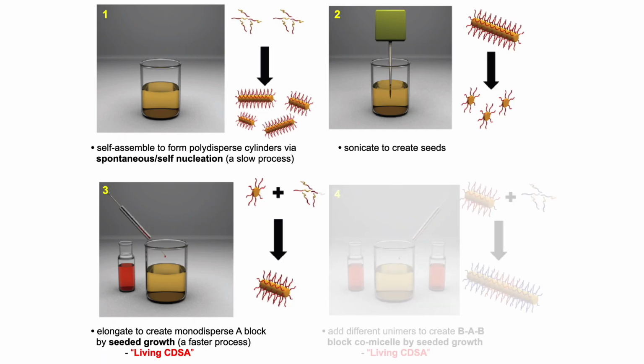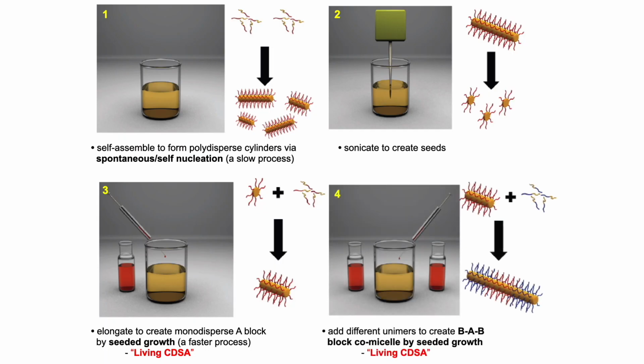Let's imagine you had a polymer that has the same core forming block, but a different corona forming block. If you add that to these structures, you grow off the end of your new polymer and generate a block structure with different corona at different places. Here's your original seed from this step, this is what you make in the third step, and now you've grown more polymer off the end, giving you different corona here.